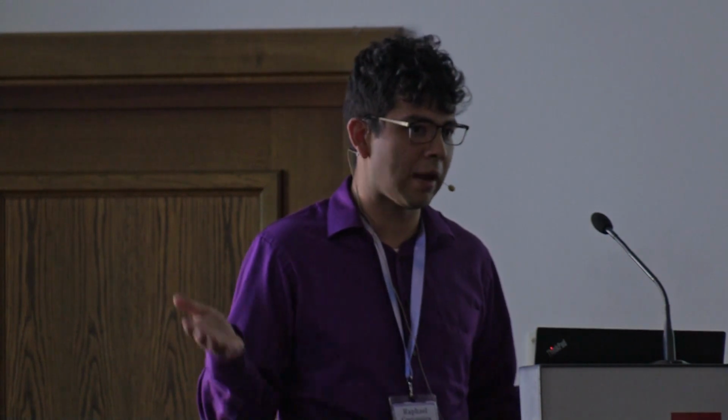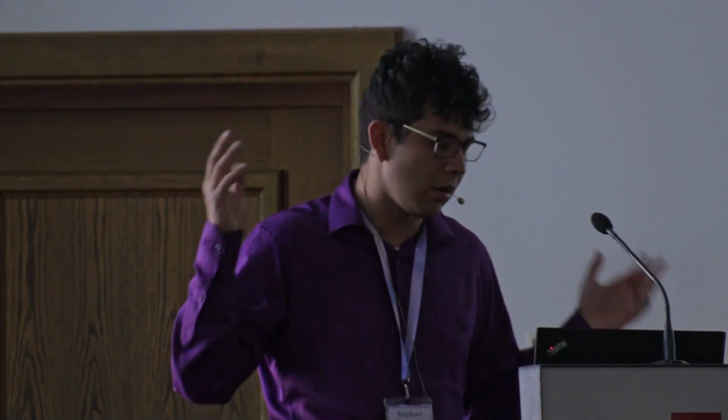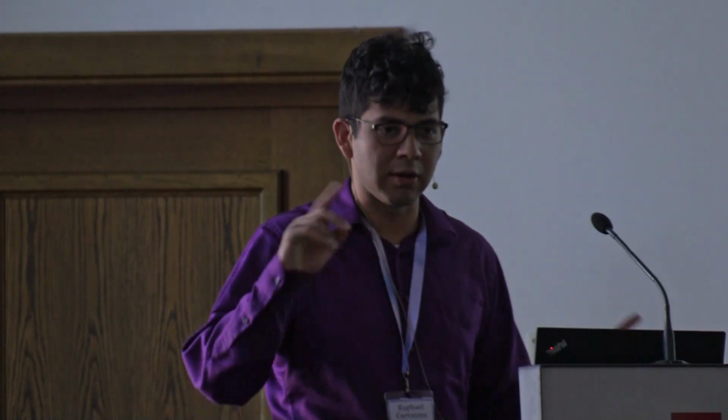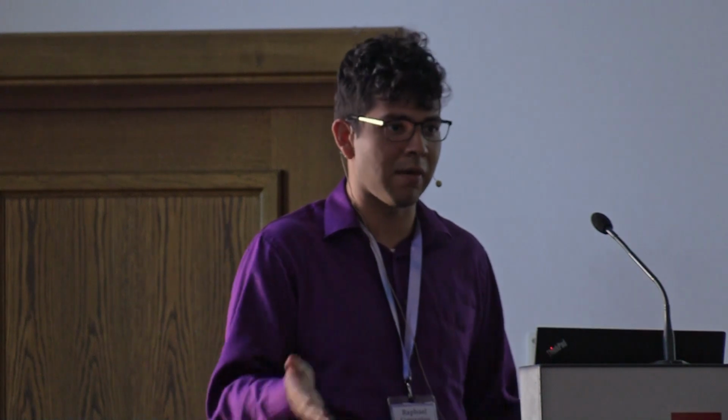Could you please explain a bit more about the TLS dissipation problem? Oh, yeah. So TLS stands for two-level systems. Usually when you build these cavities, you end up with some sort of oxide layer. And once you get to low enough temperatures, like less than 1 Kelvin, these two-level system effects start to take effect, and you just get more dissipation from this oxide layer.